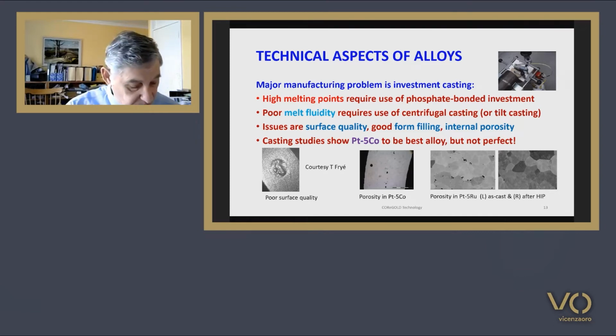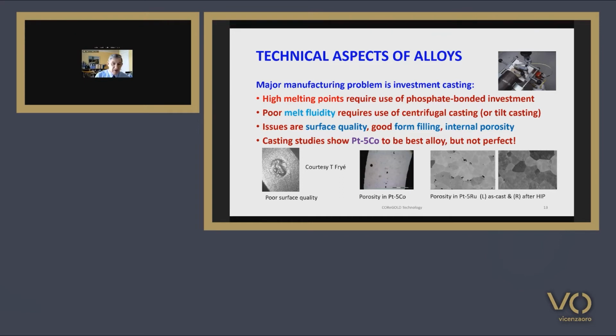The chief problem with platinum casting is getting defect-free castings, and there have been several investigations on the relative merits of different alloys, looking particularly at surface quality, form filling, and gas and shrinkage porosity. The general findings of these studies show the platinum 5% cobalt alloy to be the best of current alloys, but it is still not ideal.